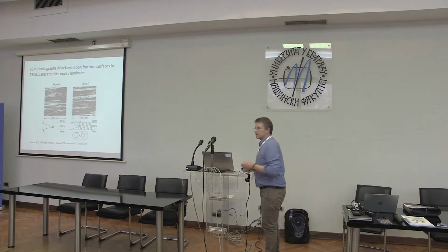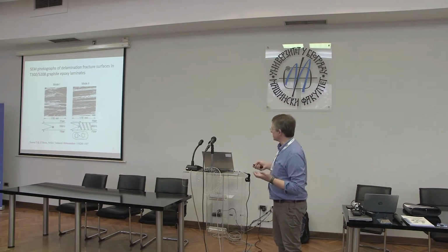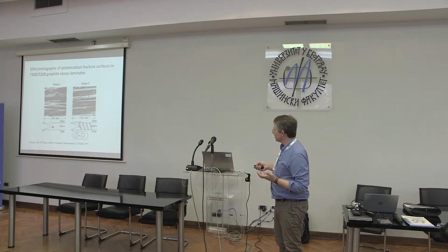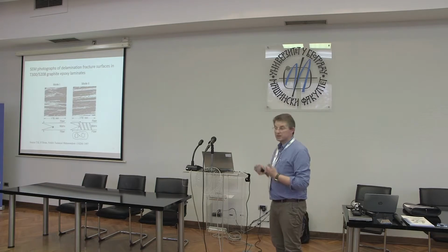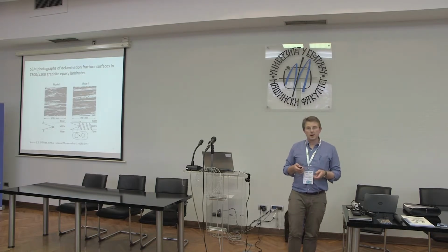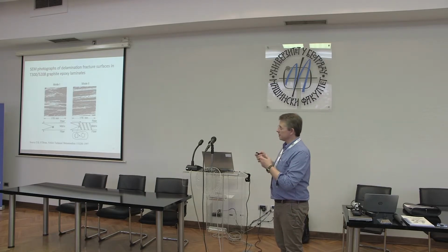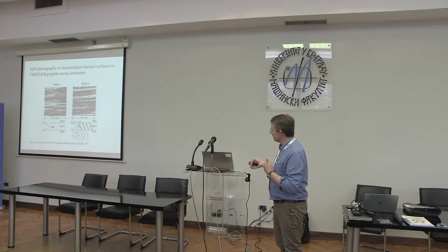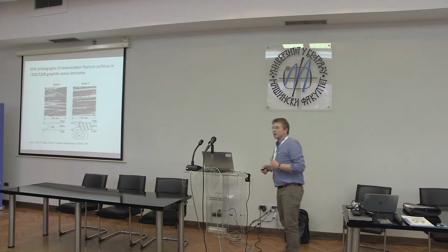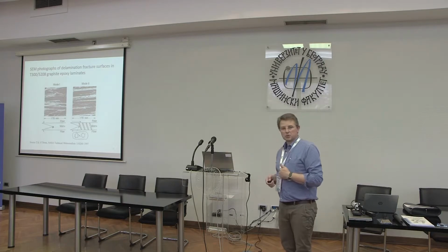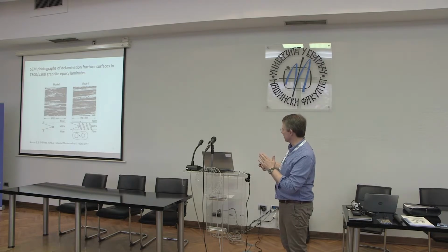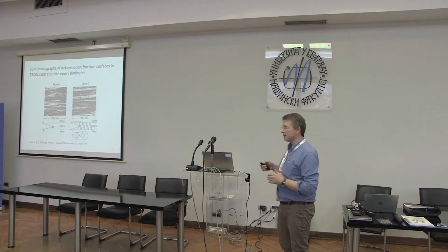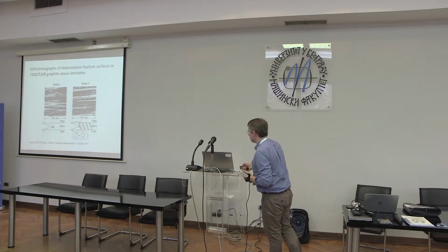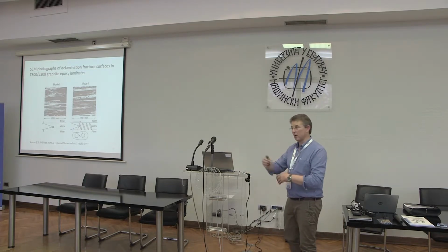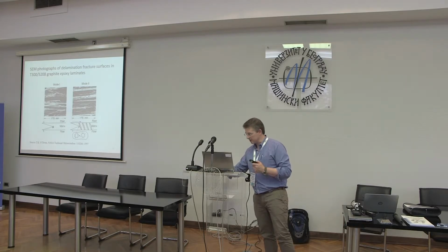The basic idea is that if you have an epoxy material behaving in a relatively brittle manner, you have a relatively small plastic zone at the crack tip, dissipating a relatively small amount of energy. Now, in the mode 2 fracture, what you have is the extended region of microcracks, which subsequently shear yield. So what happens initially is that tension microcracks open up normal to the maximum principal stress. So there's a rotation of the stress field because we're talking about mode 2 fracture, shown by the schematic here. And then these tension microcracks open up for a given length. What then happens is the crack will come along and join up these ligaments, dissipating the energy.